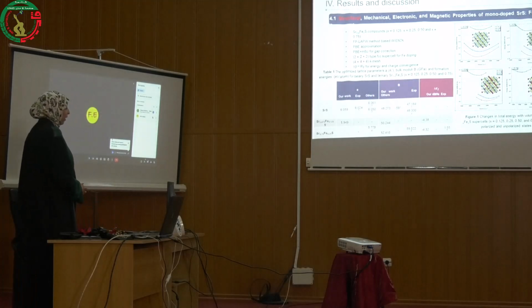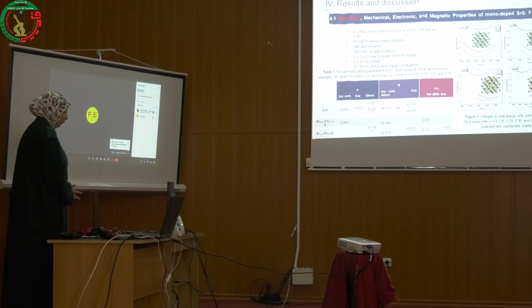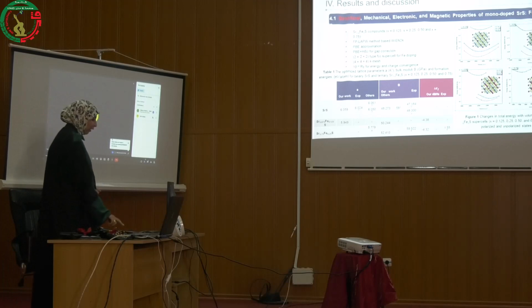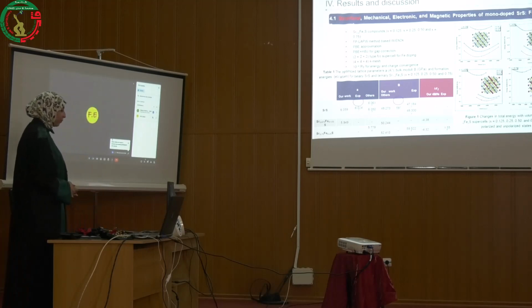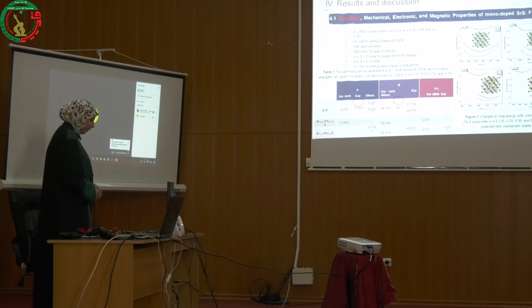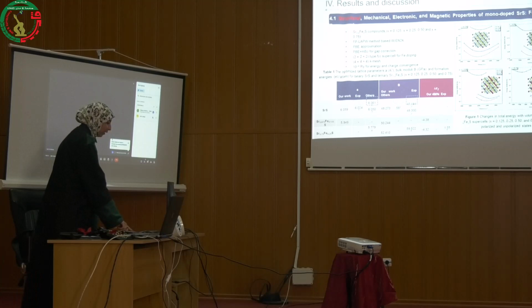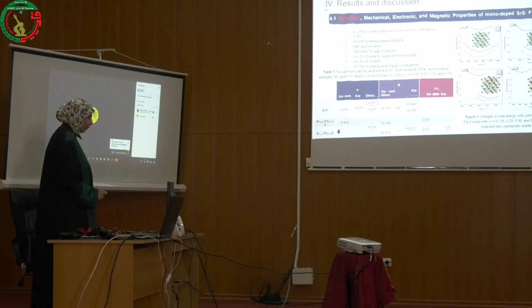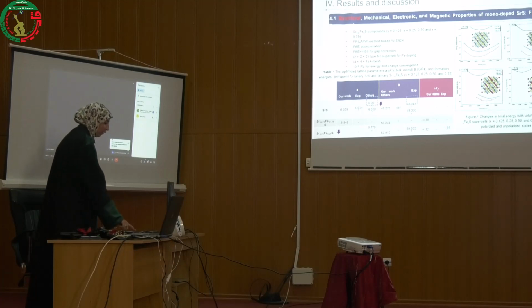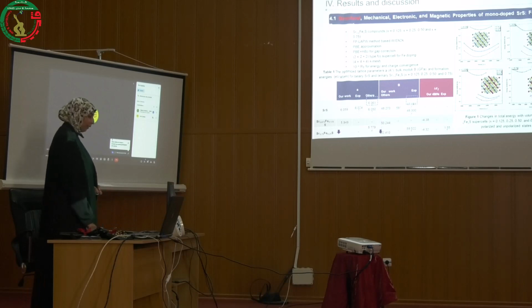In this stable phase, we have calculated the lattice parameter, the bulk modulus, and the formation energy for all the compounds, and illustrated the results in table 1. In this table, it is evident that our values are underestimated compared to experimental values, which is due to the well-known trend of DFT. However, they are in good agreement with other theoretical parameters. The lattice parameter is found to decrease with increasing concentration. The bulk modulus is also found to decrease with increasing concentration, and the formation energy values are all negative, indicating their thermodynamic stability.